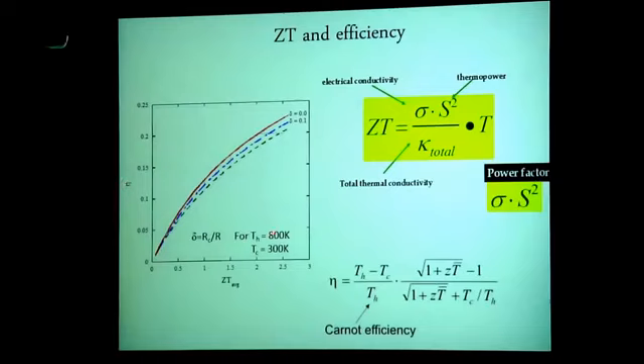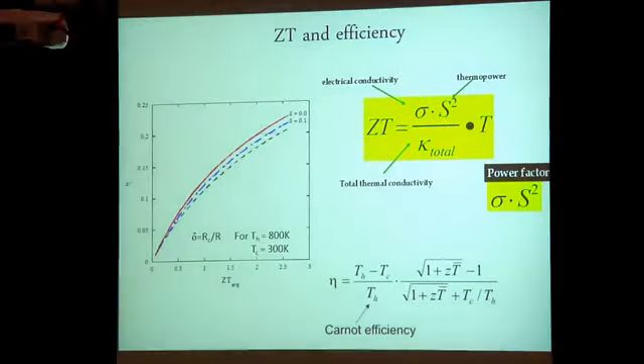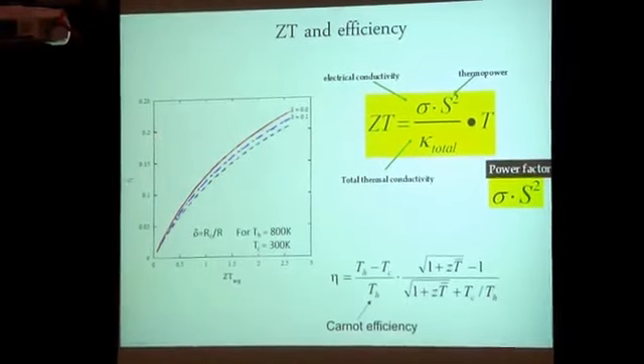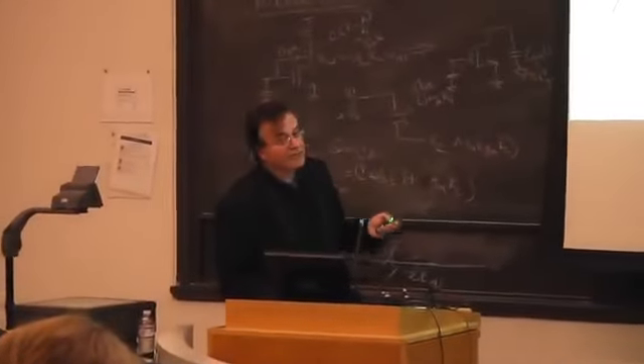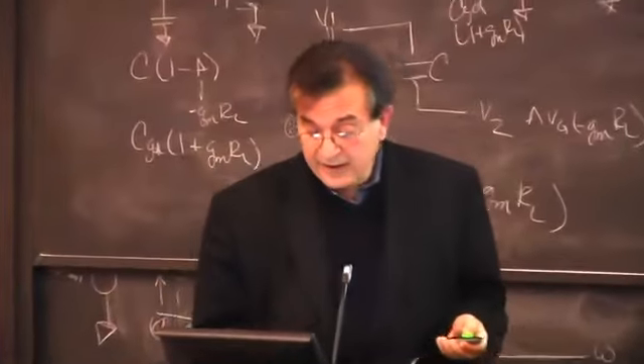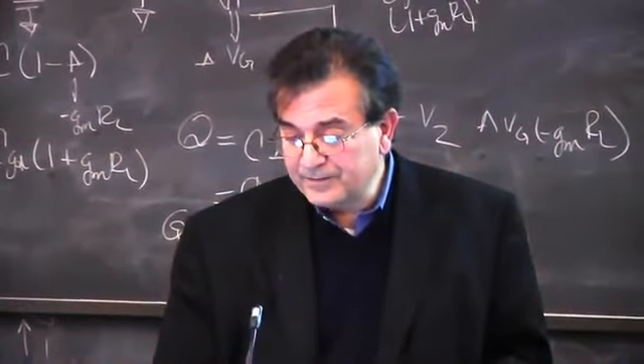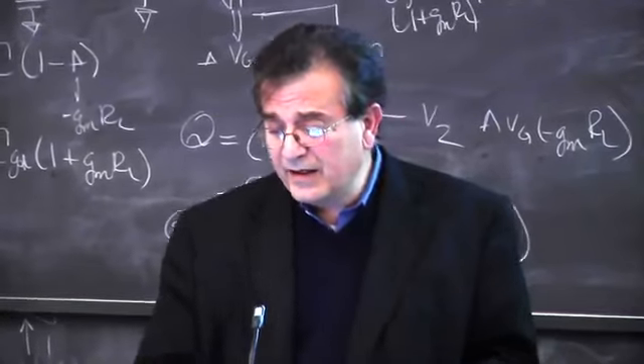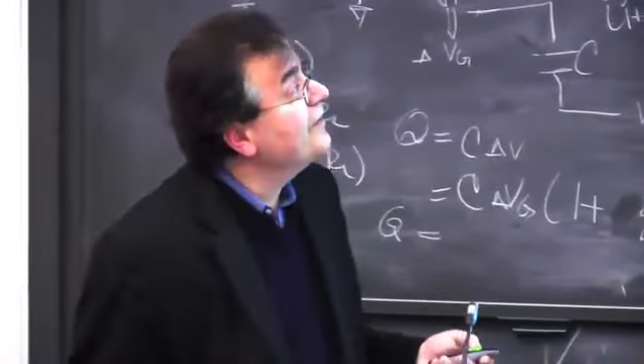So for a hot source at 800 Kelvin, cold at room temperature, if you have a ZT of 1 average, then your best device would be about over 10% efficiency. If, however, you go up to the 2s, then you go closer to the 20%. Anything between 10 and 20% conversion efficiency is huge here. It's very significant. So the higher the ZT, the better the efficiency is going to be.